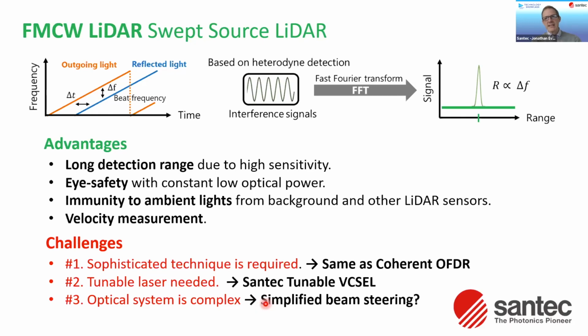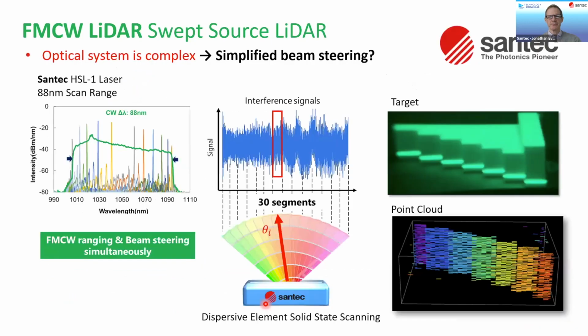What I'll present here is just a quick summary of how we're simplifying beam steering in this application. I mentioned our VCSEL laser. It's called the HSL1 laser, and this actually scans 88 nanometers in range. This is far more range than you need for the resolution required for a good LiDAR system, so it gives us an opportunity to use this together with a dispersive element to do beam steering. Here's a schematic of what we're doing: we have a dispersive element upon which our laser beam is focused. Because it's dispersing the beam via wavelength, we can segment it into different channels for ranging.